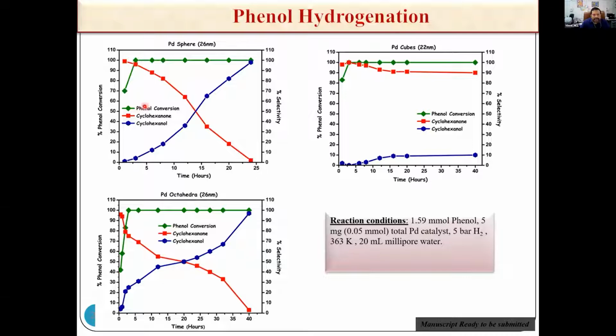And if you carry out the reaction further to 24 hours, you clearly see a shift in the selectivity. So you can clearly see that cyclohexanone, which is actually formed in the initial hours, goes down and it starts to make cyclohexanol.